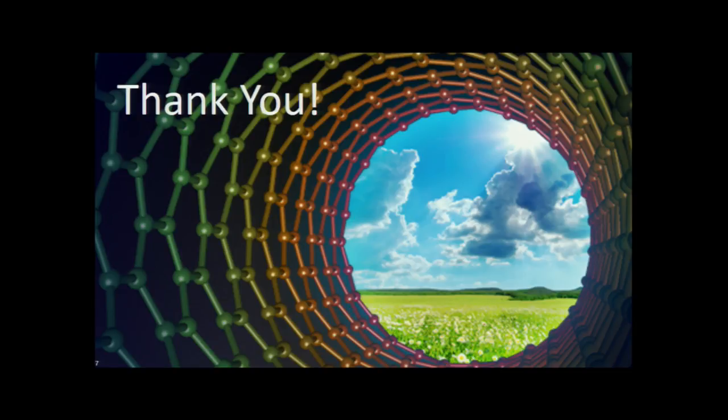Especially with the chromatography method, you even have what they call size exclusion chromatography. If you have a longer nanotube, it takes more time to travel through all these small holes or pathways. So it's relatively easier compared to electronic type. Our colleagues at NIST have a target of getting the purest material for whatever type. They spend lots of time trying to get not only a single electronic type, but also a single chirality and a single length of the nanotubes.